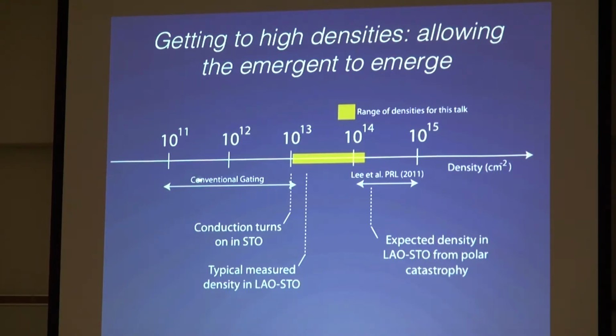And if you look at conventional gating, by which I mean a field effect setup where you have your two-dimensional electron gas, you have an insulator, and you have a metal. You capacitively couple that metal to the two-dimensional electron gas. Conventional gating can only get you so far before you usually have dielectric breakdown. So for very nice films of alumina grown by ALD, you can get changes in density of about 1 times 10 to the 13th per centimeter squared, which is not enough to really deal with this correlated phenomenon that exists in complex oxides.